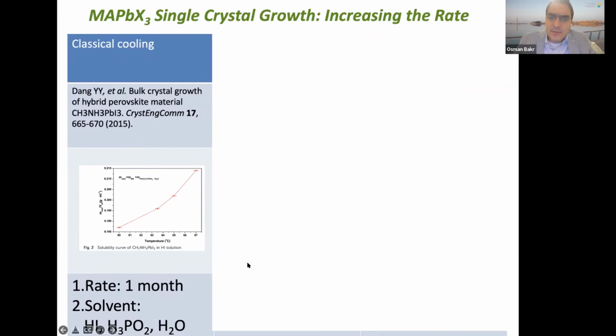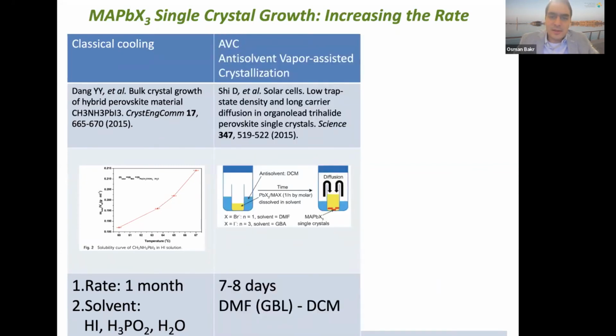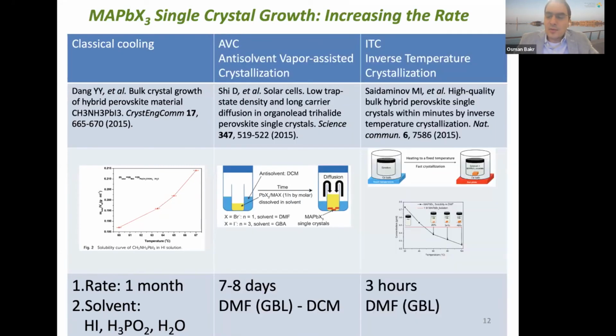But if it took one week to grow perovskite single crystals, is that practical? How can we use crystals that take a week to grow? And sometimes, even with other classical methods, it can take up to a month to grow. So we started looking at different methods to grow crystals, and by chance we discovered a method that allows us to grow large crystals within minutes and sometimes in hours as well.